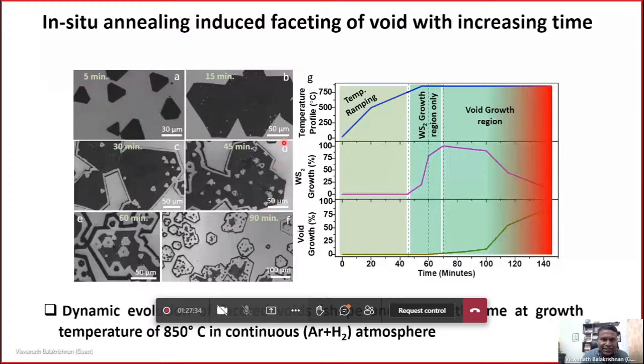I can see that some of them are 50 micron, some are 30 micron. Just to clarify, we are not looking at the same sample. These are different growths, different flakes. In this growth, we did post-growth annealing of 5 minutes. In another growth, the post-growth annealing time was changed to 15 minutes, 30 minutes, 45 minutes. Since we are looking at different samples, imaging could not be done with the same magnification, but we want to cover what we are looking for.